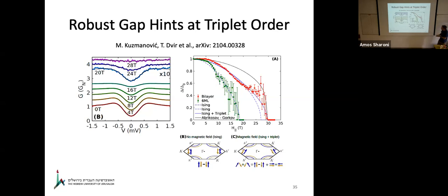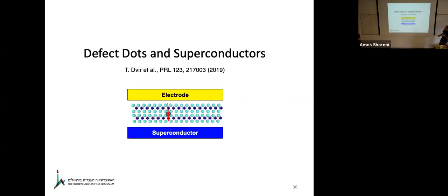Some theory by my colleague Maxime Chodas claims that it becomes a triplet superconductor, because you have these two spins tilted in the plane, and then you have this triplet component. Okay, so maybe it was more than 60 seconds, but that's everything we did, which does not involve defects. What happens if you do have defects?